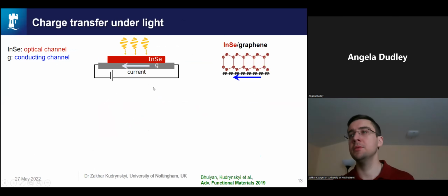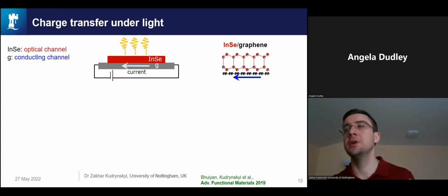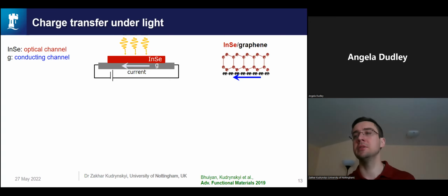So this shows that we have a good charge transfer between the two layers, which we can also probe by light. So now in this experiment, we have a similar structure to the one that I showed you before. Here we have a conducting channel and an encapsulating layer. So indium selenide is the optically active layer.